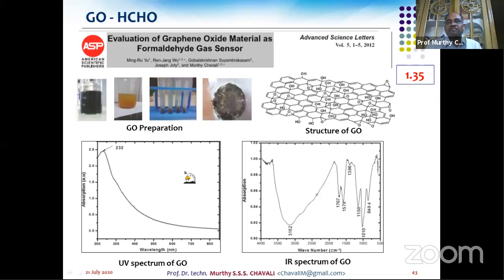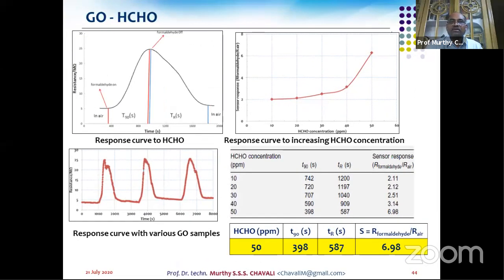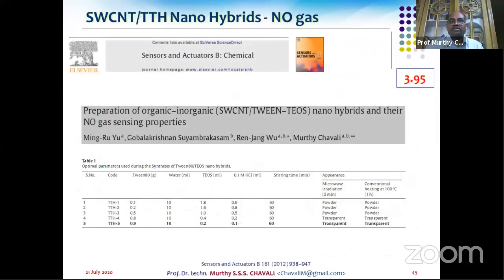It's a volatile material converted into gas and then carefully studied for gas sensing for a liquid. So the response also looks very good, and we have published this in 2-3 journals with important enhancement in our studies. And then after this, we went into nano hybrids. Instead of preparing these hybrids, which takes 1 to 2 days, we wanted to prepare these hybrids using microwave techniques. Same thing for NO gas, but with the microwave technique, we were able to develop these hybrids within 5 to 6 seconds. And the same has been studied and published in Sensors and Actuators journal for these hybrids.